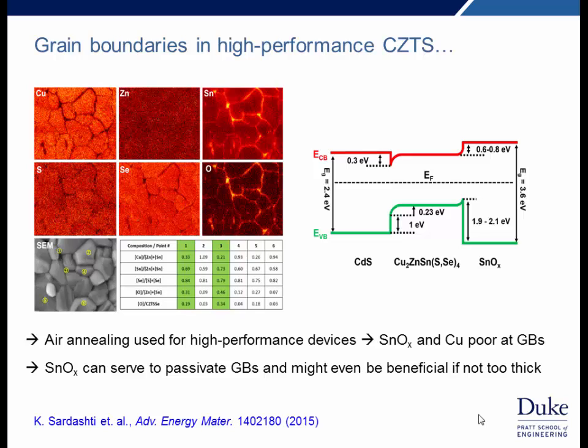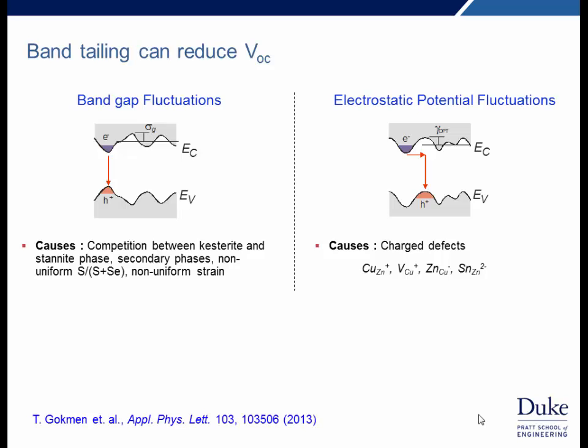And if you also look at the energetic offset of the bands at this interface, you could see that electrons are basically repelled from this interface. And so there's going to be reduced opportunity for recombination at these grain boundaries. And so the tin oxide can serve to passivate the grain boundaries if it's not too thick. And so these are some of the issues with interfaces and grain boundaries.